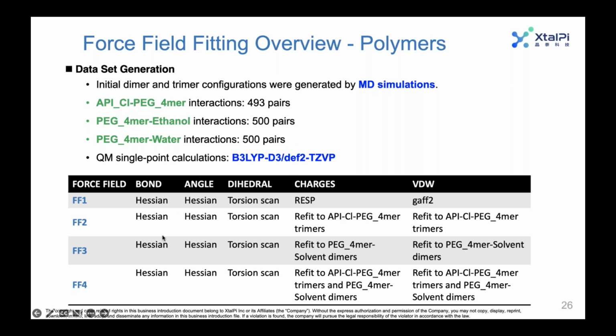And then we trained a number of force fields based on those interaction energies, and we ended up going with force field model 4 in this case, which takes into account the interaction between the salt and the polymers, and also trimers of the polymer units and the solvents.